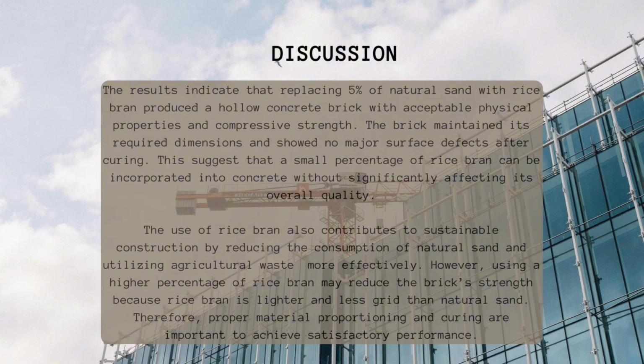In addition, using rice bran helps reduce agricultural waste and decreases the demand for natural sand. This makes the brick more environmentally friendly and supports sustainable construction practices. However, if too much rice bran is used, the brick may become weaker because rice bran has lower strength than natural sand. Therefore, the replacement percentage should be carefully controlled to achieve a balance between sustainability and mechanical performance. Overall, 5% rice bran can be considered a suitable partial replacement for natural sand in hollow concrete brick production.